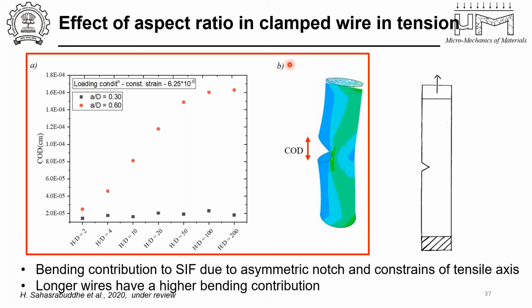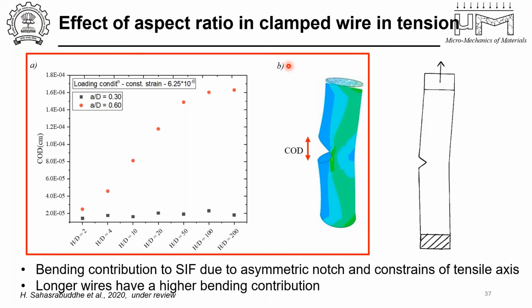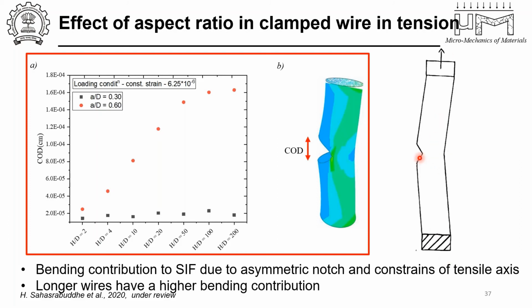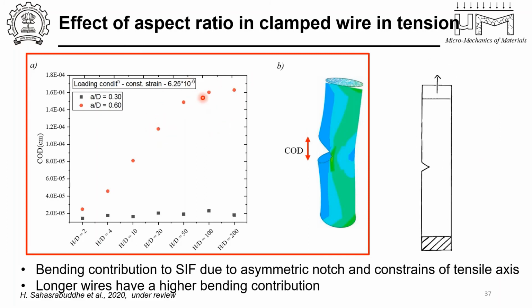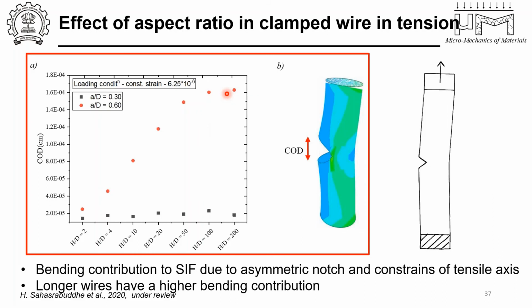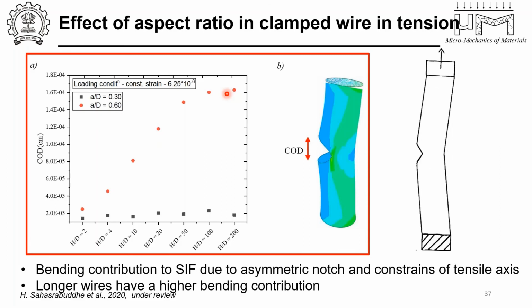Now, why is there the aspect ratio effect at all? That is what we're trying to show here. So suppose you have a tensile sample with an asymmetric notch, that is a one-sided notch. That causes a bending contribution to come up because the tensile axis is constrained. So when the crack opens up here, this leads to bending in the x direction. So that bending contribution increases the K1. The COD going up also shows that there is an increase in the K1 for longer aspect ratio wires, whereas that is smaller for the shorter aspect ratio wires. This is all for the same applied far field stress. So the stress is constant here.